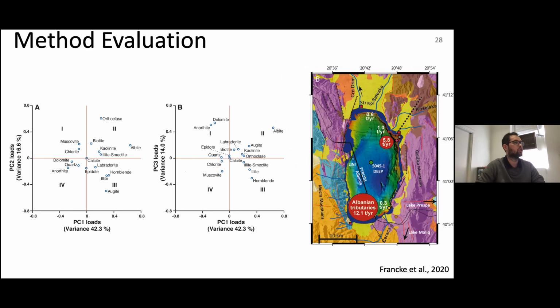We also took a bit more of a look into whether changes in sediment supply mineralogy have any major control on our activity ratio. And with the help of Brian Jones, we did a lot of XRD on this late glacial to Holocene record from the DEEP site, with the idea of trying to align the mineralogy to the different lithologies we find in the catchment. And you see that here already. That's a nice scatter plot. It's really difficult, almost impossible, to assign any clusters in this principal component analysis from these both sides, principal components between the first three principal components, to any of the lithology in the catchment.